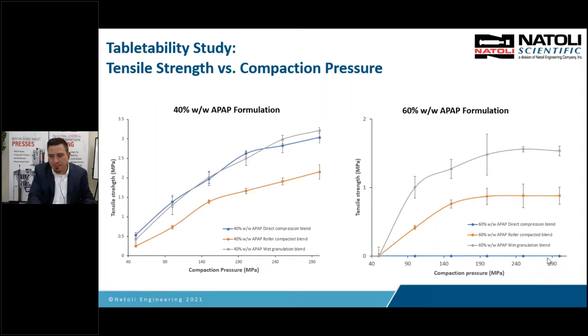Okay, so let's look at 40%. We're looking at tensile strength as a function of compaction pressure again. To achieve 2 megapascal, you'll see we now need to run the direct compression and the wet granulation at about 150 megapascal, which is still very reasonable for a pharmaceutical product. And then the roller compacted blend, you're going to have to go closer to like 220 megapascal, which is on the higher end, but 220 is still reasonable. It's not excessive. We're getting closer to 300, which is starting to be excessive.